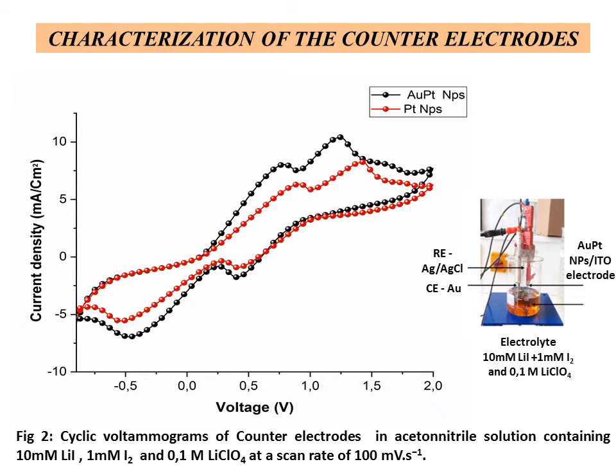As shown in the cyclic voltammograms, the oxidation and reduction peaks of triiodide were superior for the gold and platinum counter electrode compared to the platinum electrode. However, the larger peak currents of triiodide oxidation and reduction were observed on the gold-platinum electrode, revealing that the electrocatalytic activity toward this redox reaction at the nanoparticle gold and platinum electrode was improved.